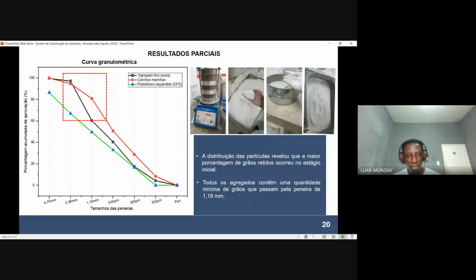Based on the kinetic results, the EPS mortar tends to demonstrate a coarse-like behavior, as clearly seen from the graph here, compared to the seashell mortar and the fine aggregate. It demonstrates the coarse-like behavior of an aggregate, but as the sieve sizes decrease, it tends to attain fine aggregate properties. The percentage of retention of this material diminishes compared to other materials, but as it passes through the various sieve sizes, it behaves like a fine aggregate compared to the seashell aggregate and the fine aggregate.